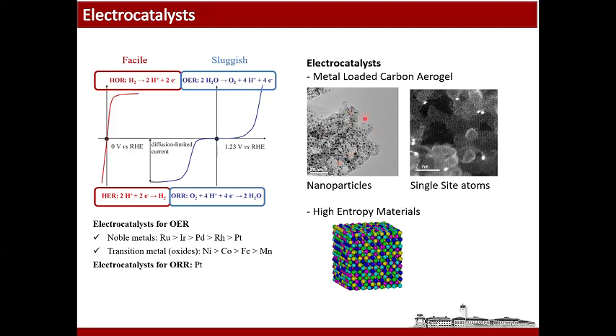So instead of using such a high number of nanoparticles, a high number of platinum atoms, we can disperse those particles onto the graphitic structure as single sites, which is still active, still with a very high efficiency, but the number of atoms is low in this case. I mean, these two materials give a similar efficiency, but the amount of noble metals used in the single atom structure is low. Or we can use only transition metals without any noble metals, and then produce high entropy materials, and they might still be active. So I will talk about high entropy materials.